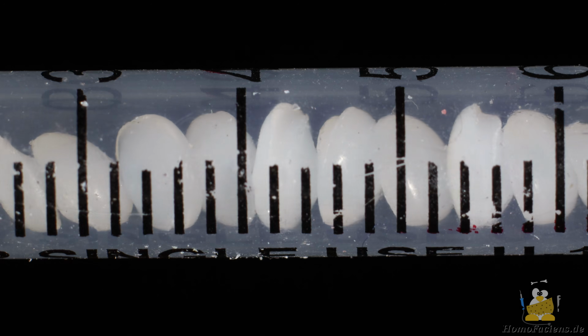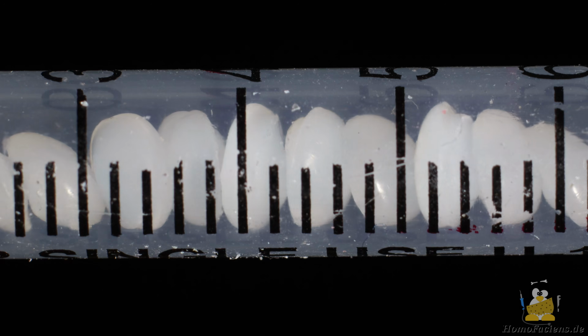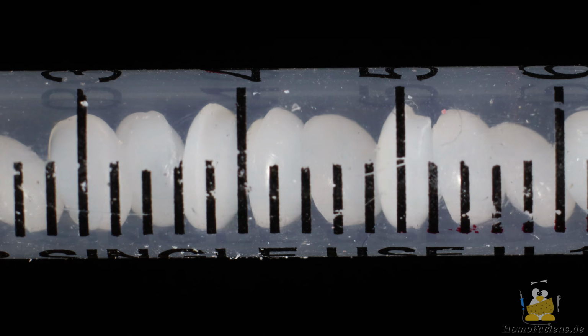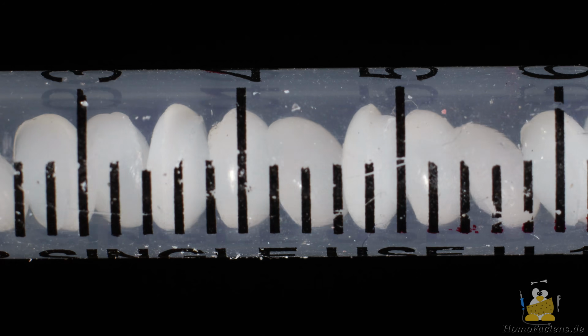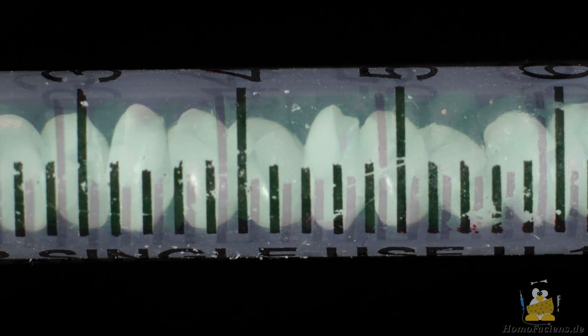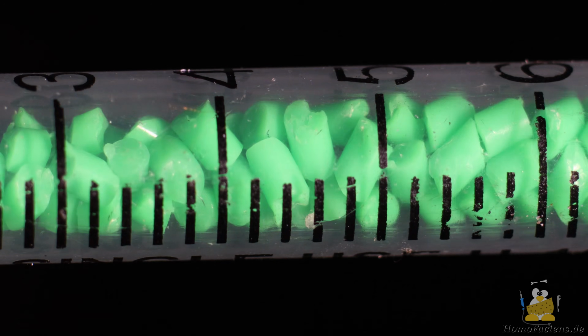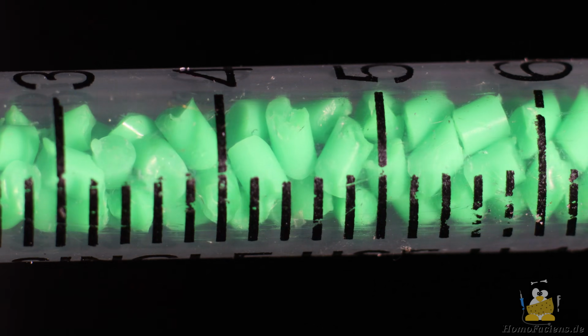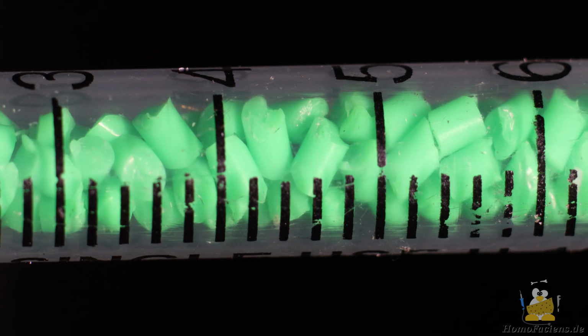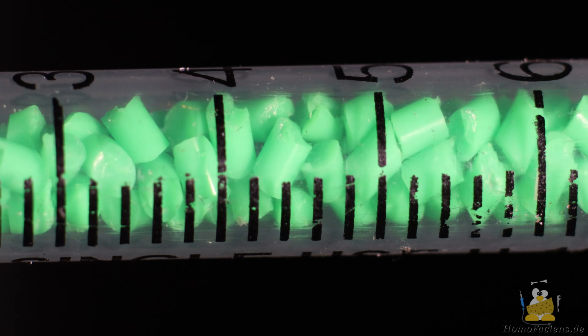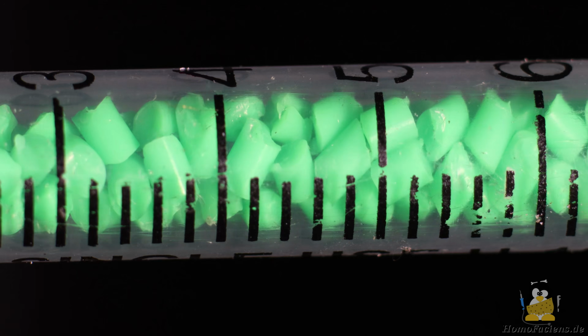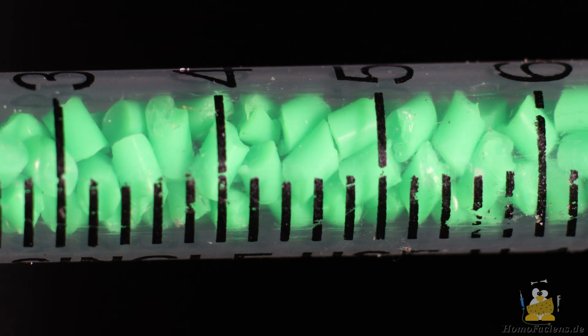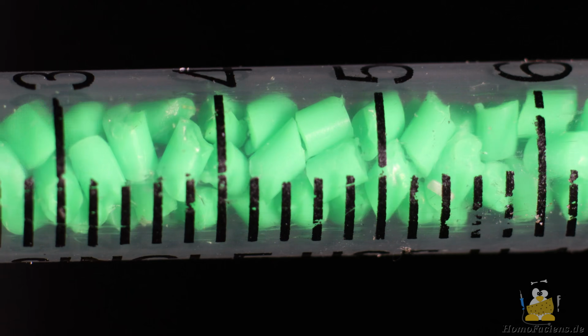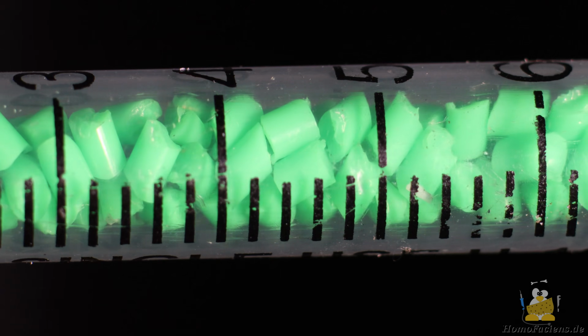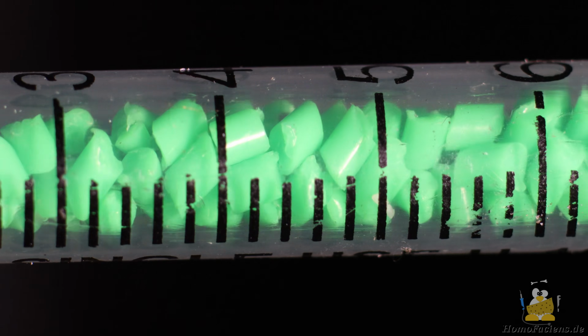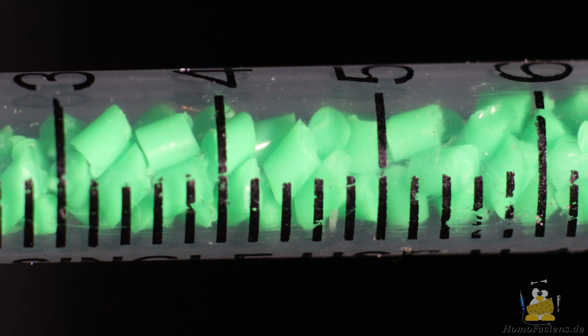Consequently, if the granules are lined up like beads on a string and set in motion, the material exhibits noticeable density fluctuations during extrusion. This effect can also be observed with pellets. The sharp edges at the ends of the pellets cause the material to choke on itself and the tube walls, resulting in a more pronounced wave motion than is the case with the granules.